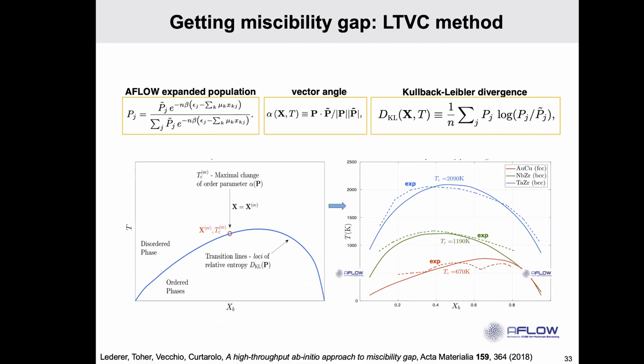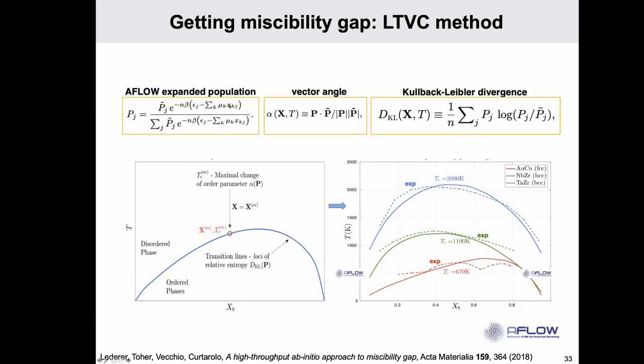And then, thanks to the Boltzmann coefficients here, we calculate what is the probability of occupancy, right? So pretty much it is the exponential of minus beta, the energy, for all the energies that we have calculated, right? So it's a huge vector, okay? Hundreds of dimensions, okay? And then instead of the energy here, you calculate the deformation energy. That's why you have the mu, which are the references and the concentration. Anyway, so this is what it is.